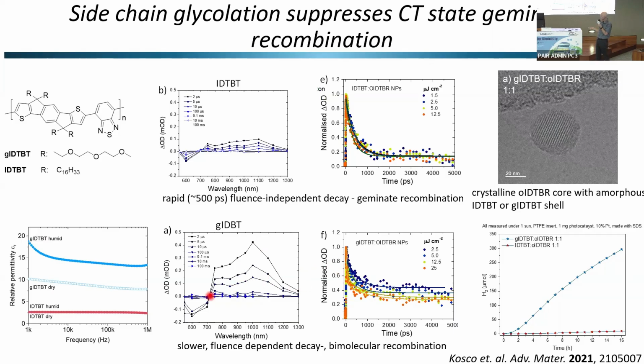Having this glycolation, again, we can see this really rapid effect. If you compare non-glycolated and glycolated transient absorptions, firstly, you can see that the intensity of the absorption is much higher, but also that the decay is different. So this is a geminate decay, a fluence-independent decay. When we look at the decay as a function of radiation intensity, it's pretty similar. And that tells you that the recombination occurs within the same exciton, so it's geminate recombination. In the case of our glycolated IDTBT, it's a bimolecular recombination. We're forming more free charge carriers, and the way that they recombine is through bimolecular processes.